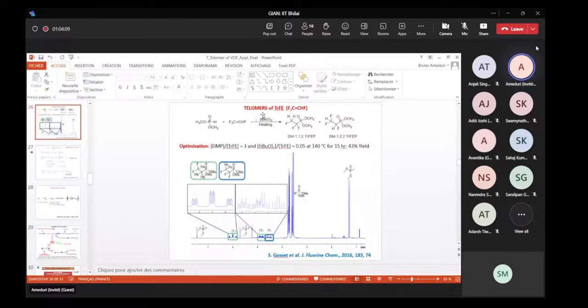And as you may know, on liquid electrolyte for batteries, there are some issues of fire. And the presence of phosphorus enables to increase the fire resistance. So our strategy was to try to find out, was it possible to make a monoadduct of trifluoroethylene with this dimethyl hydrogenophosphonate? And the answer is yes.